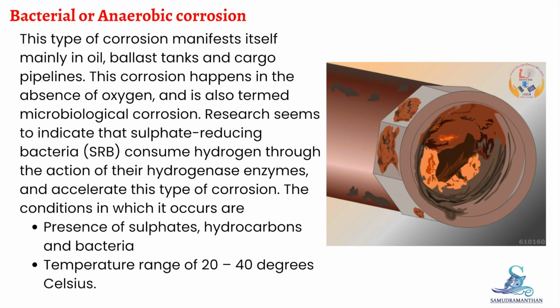Another important form of corrosion is bacterial or anaerobic corrosion, also known as microbiological corrosion. This occurs mainly in oil tanks, ballast tanks, and cargo pipelines, and takes place in the absence of oxygen. Research indicates that sulfate-reducing bacteria, or SRB, consume hydrogen through their hydrogenase enzymes and accelerate corrosion. This type of corrosion occurs when sulfates, hydrocarbons, and bacteria are present, particularly within a temperature range of 20 to 40 degrees Celsius.